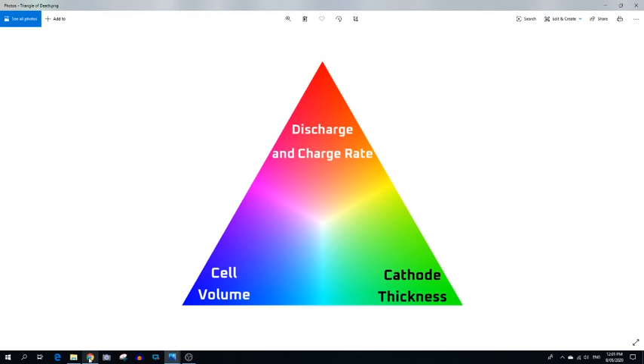Of course, discharge and charge rate, those are positives. The reason you'd want a thick cathode is that if you just increase the cathode thickness by 25%, you get about a 10% specific energy increase. That would be going from like 300 to 330 watt hours a kg. Cell volume, if you just increase it by a small amount, say when Tesla went from 18650 to 2170, that small increase reduced the number of cells they needed to create by about 30%. And with 30% fewer cells, you have 30% fewer welds, 30% fewer separators, 30% fewer cell cans. It makes it a lot cheaper and easier to manufacture the battery pack.